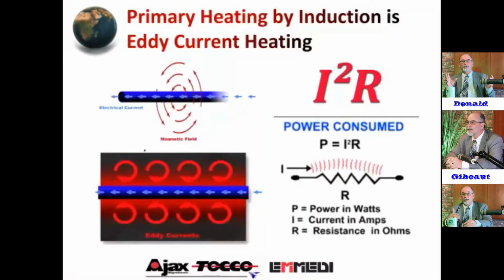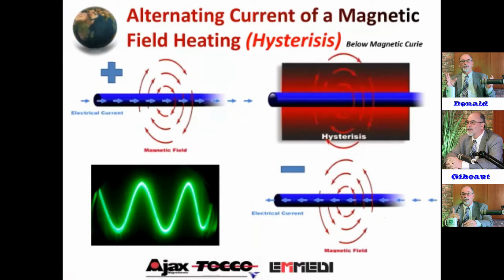Now, going into the technology, the primary heating is I squared R loss. The same principle as a nichrome wire. You have current flowing against a resistance that generates heat. So that's the primary heating principle here. But there's also, when you get below the magnetic Curie point, a hysteresis heating, which adds to the efficiency. And typically for a 0.3 carbon, that's somewhere around 1400 degrees Fahrenheit, and we're pulsing, like you see on the sine wave to the lower left on an oscilloscope, above and below the line of polarity. So we're pulsing positive, then negative to make one complete cycle.